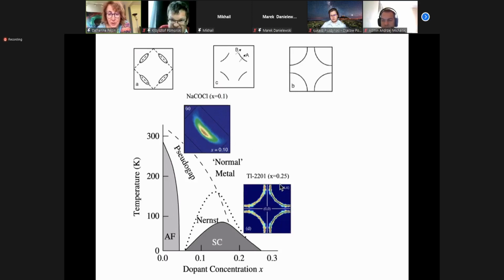And here I show what we observe. On the left-hand side, this is ARPES, angle-resolved photoemission. On the left-hand side, they were never able to do it because there is too much disorder. So these hole pockets have never been observed experimentally. But on the right-hand side, we see the large Fermi surface, which is typical of a Fermi liquid. So Landau's Fermi liquid theory is seemingly valid on the right-hand side of the phase diagram. And in the middle, we see this weird banana shape that we call Fermi arcs, schematized in figure B. Basically, the electrons are gapless, but only on arcs.